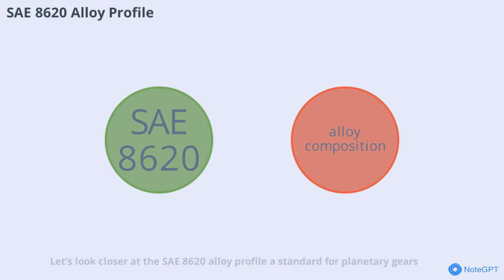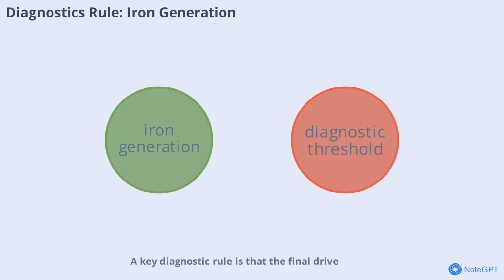Let's look closer at the SAE 8620 alloy profile, a standard for planetary gears. This alloy is composed of about 96.8% iron with small additions of chromium, nickel, and molybdenum. Each element plays a role. Iron provides strength, chromium adds surface hardness, nickel increases toughness, and molybdenum improves wear resistance. When oil analysis detects elevated levels of these metals, it can indicate specific gear wear or alloy breakdown, guiding targeted maintenance actions. Key diagnostic rule is that the final drive generates significantly more iron per hour than a differential.